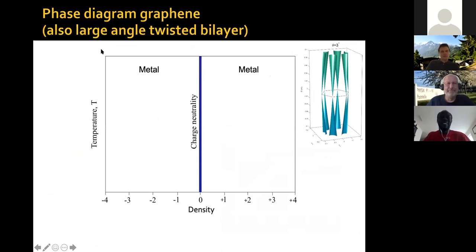So this is the phase diagram, temperature versus density for graphene and also for large angle twisted bilayer graphene, okay? The electronic structure is just these Dirac cones, and there's only one interesting point. That's the charge neutrality, often also called the Dirac point, okay? On both sides of this is a metal. At charge neutrality, you're in a semi-metallic behavior, but graphene conducts everywhere in this phase diagram.